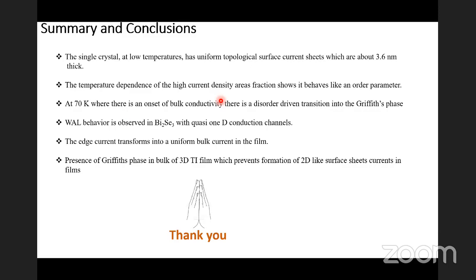So the local ordered regions have short range order, which is the Griffiths phase. The local pockets with short range order have the Dirac-like electrons, surrounded by the normal electrons which are generated by disorder. And we feel that this is also the reason which destroys the 2D surface states inside Bi2Se3, the observation of 2D surface current sheets in Bi2Se3.